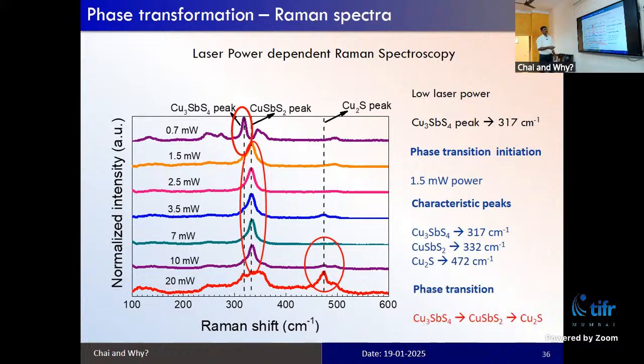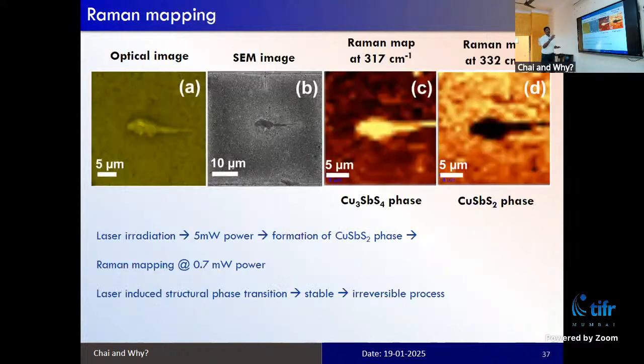So the phase transition happens from Cu3SbS4 to CuSbS2, and then finally it degrades into Cu2S. This can be visualized using a Raman mapping of the Raman spectra of this material. We have intentionally irradiated a small region using a high laser power, something around 5 milliwatt or 10 milliwatt, and we did a Raman mapping.